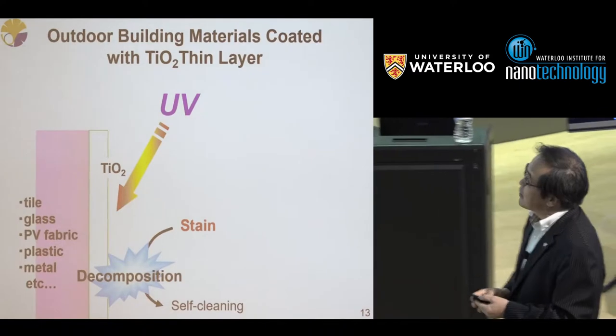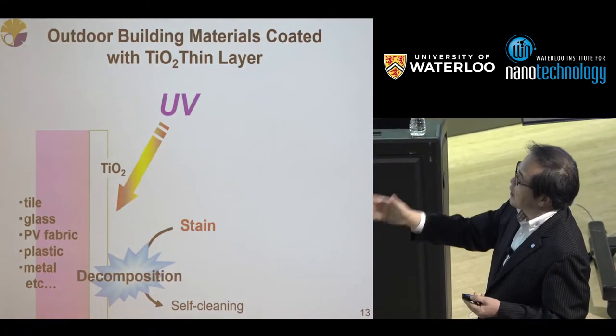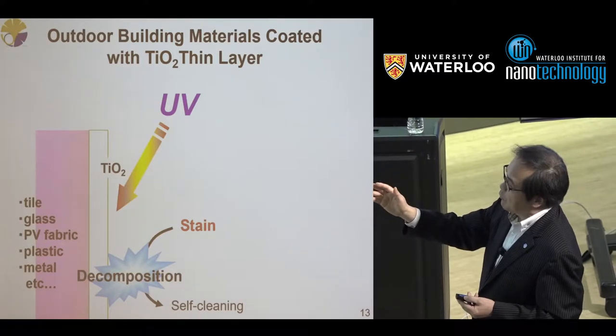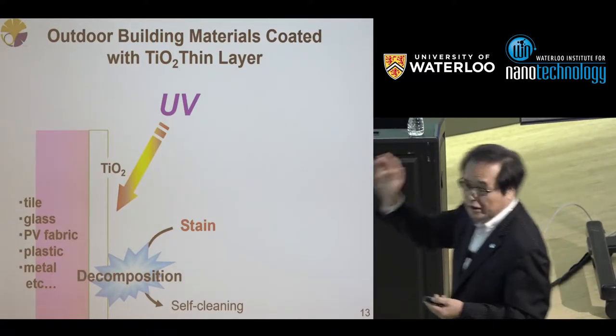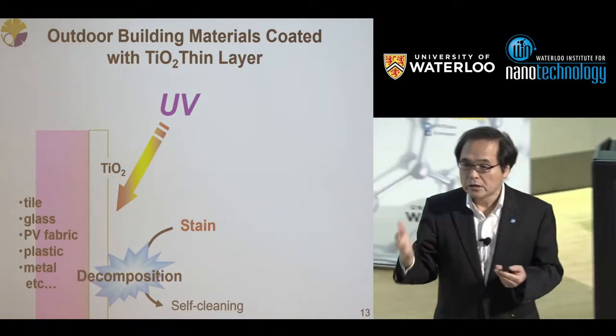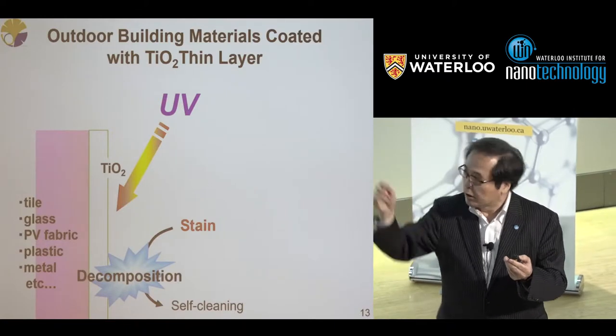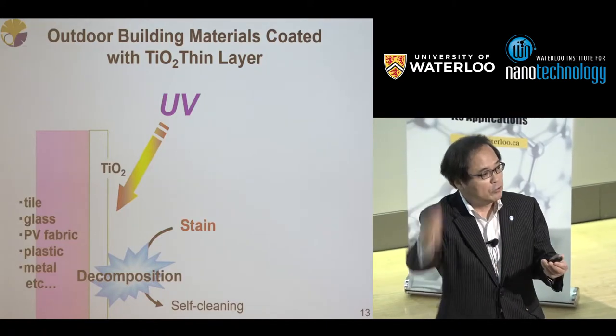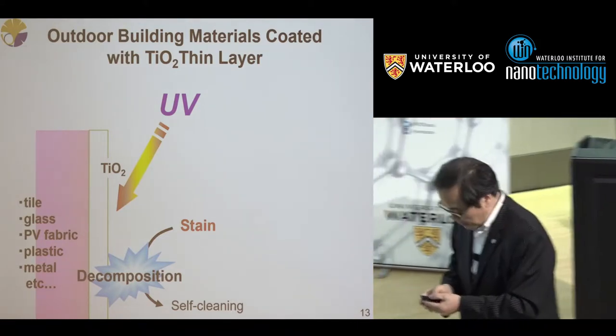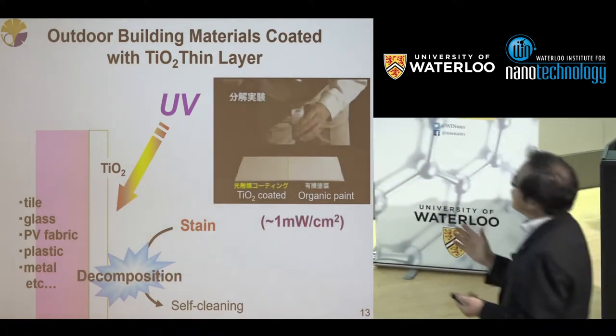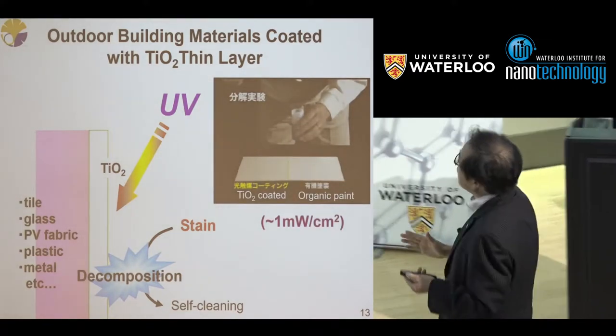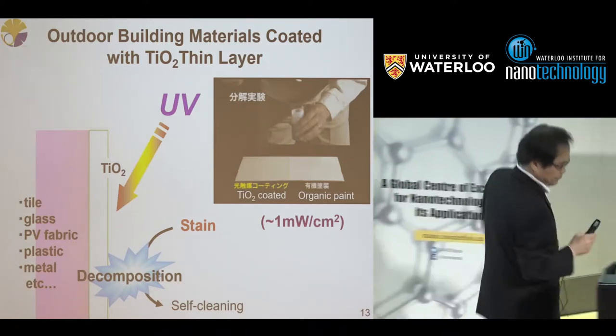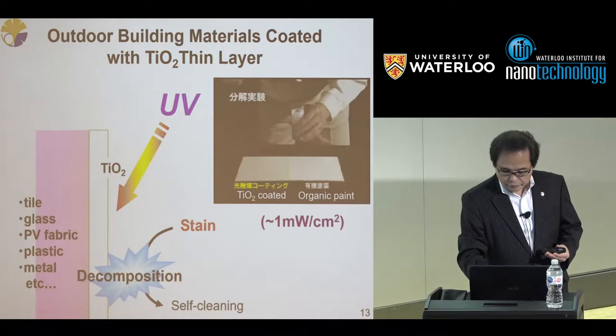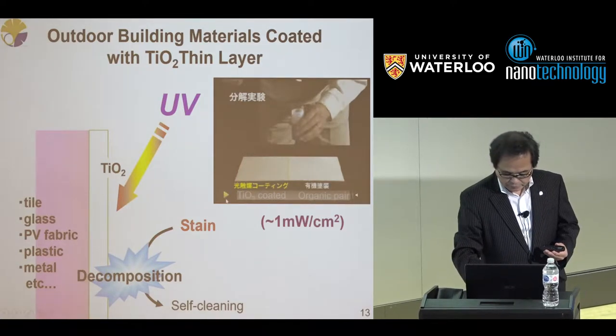However, the idea was to coat outdoor building materials like ceramics, glass, polyvinyl fabric, plastic, metal, something like that, with titanium dioxide, using, as I told, the proper method: such active titanium dioxide dispersed in the proper binder and coated. Then we can have a transparent film. Then expose it outdoors. Outdoor light intensity is 1 milliwatt per square centimeter, that's why it works. Okay, this is a simple experiment. The left-hand side is titanium dioxide coated, the right-hand side is the conventional substrate, illuminated with 1 milliwatt per square centimeter, typical light intensity.